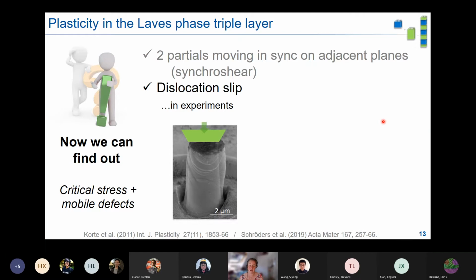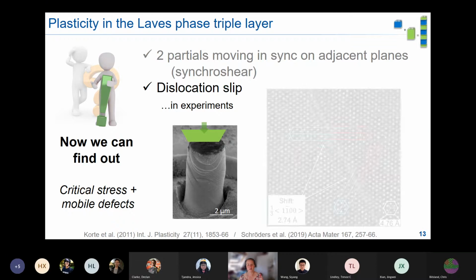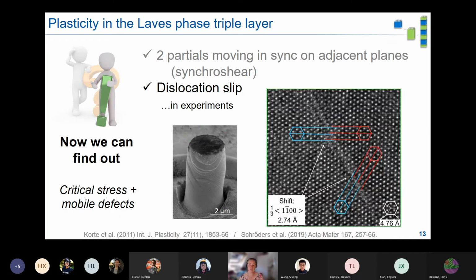So we can suppress cracking in small volumes using micropillar compression, and by that we can actually then get deformation, and importantly we can also pull out samples that we can meaningfully put into the TEM and analyze all the way to, again, high resolution imaging, where we can find out which dislocations were actually active in our material. So we can measure critical stresses and we can see which mobile defects we have in our material.